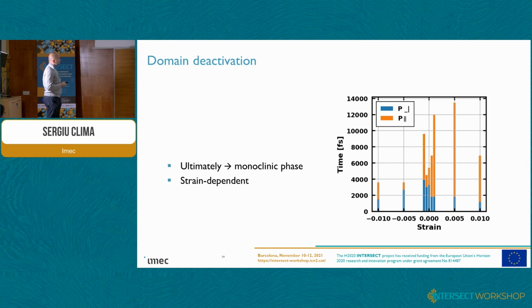So this shows that the strain will have a great influence on whether you get disappearance of the polarization, so fatigue mechanism. Eventually you can think of it as wake up, for example. If it's parallel to the surface, then it becomes perpendicular. That could be happening during the wake up phase, for example.